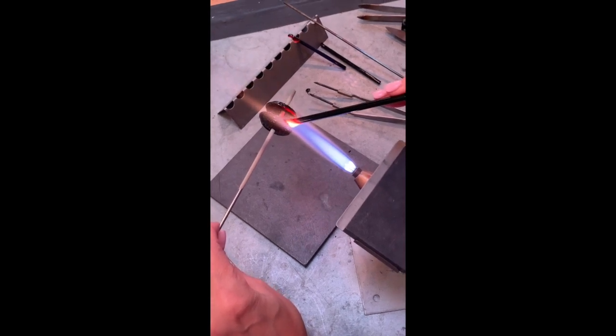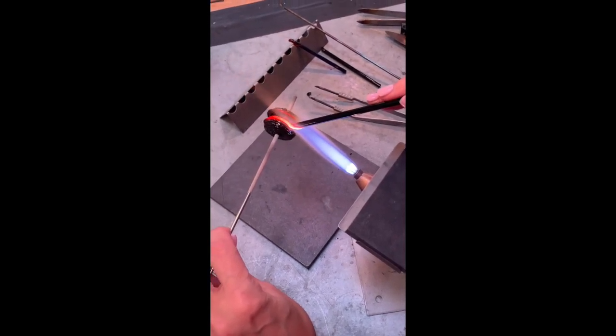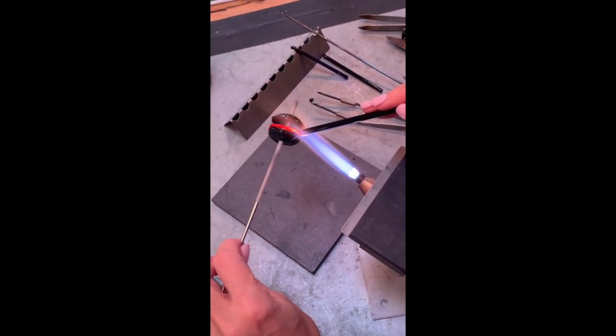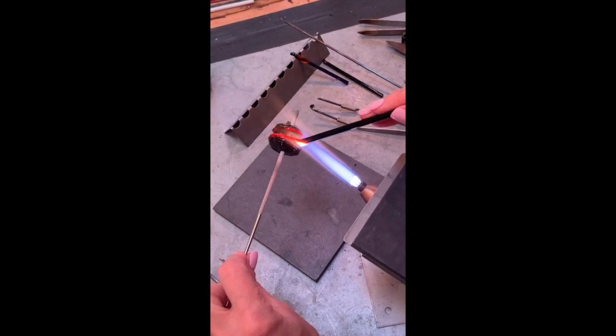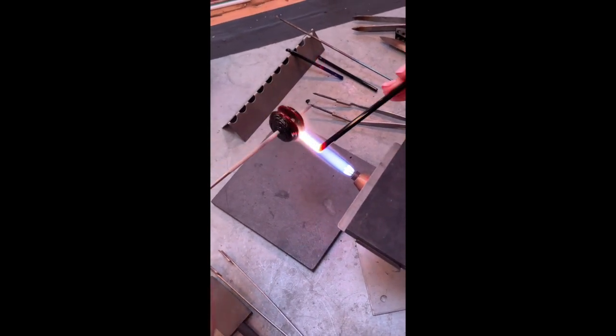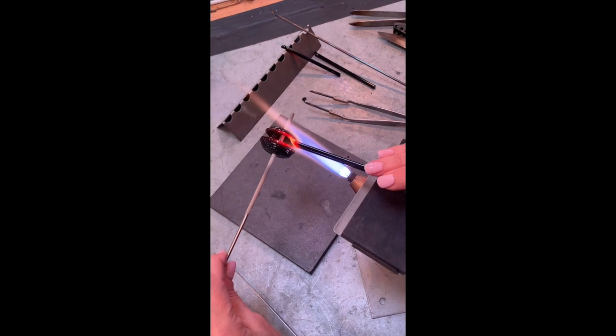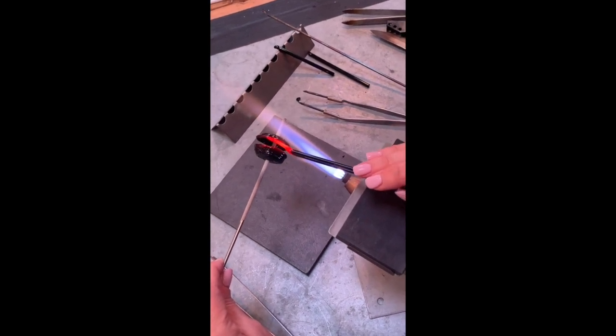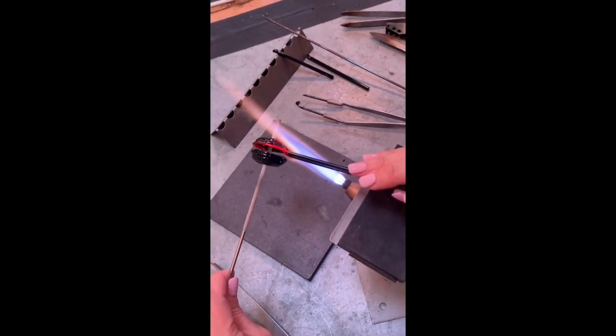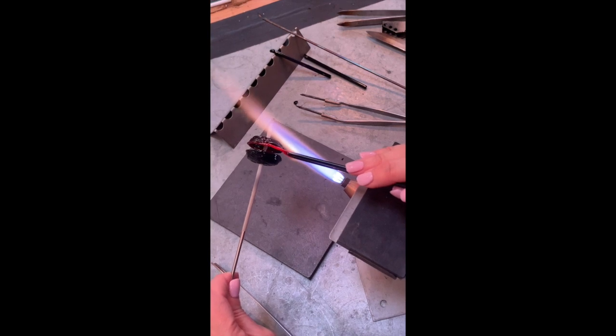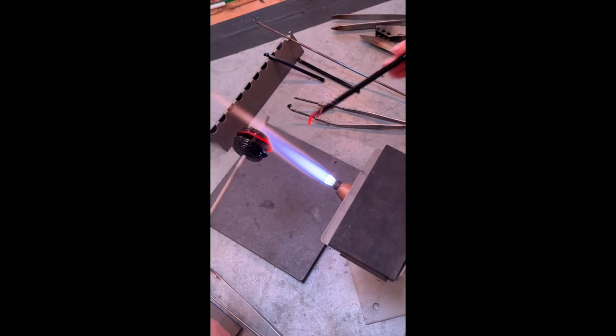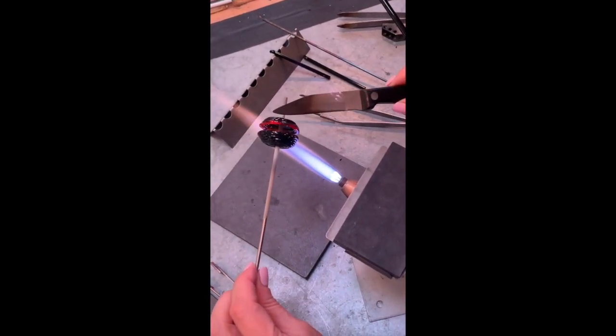And just like when I'm using a solid mandrel, I'm building them toward each other and trying not to have pinholes that I'm going to have to go back and patch. Well, how do you avoid the pinholes? We'll talk about that in the video on troubleshooting, which I'm going to do in a couple of days. But the shortest answer at the moment is make sure that you are adding molten glass to fairly warm, almost hot glass.